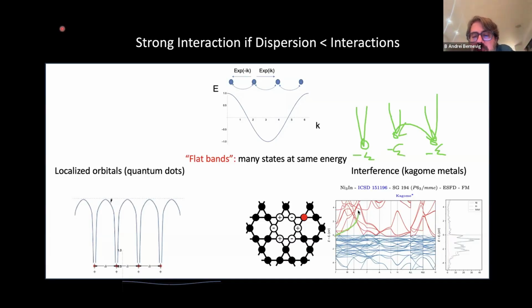But you can see that many bands here do have tons of dispersion. This is electron volts. It's a huge dispersion. So you can see that even though there's many bands that have dispersion, then you do have hopping. The electrons are not pinned at sites, but you still have some flat bands.